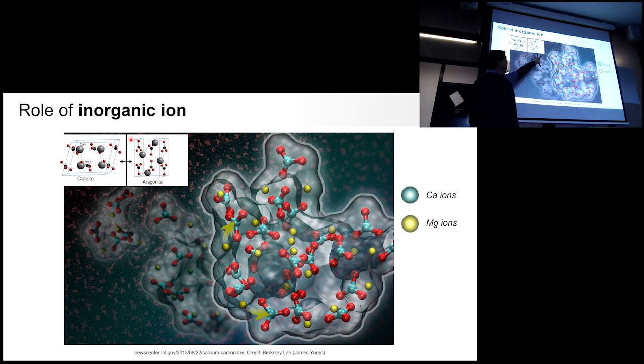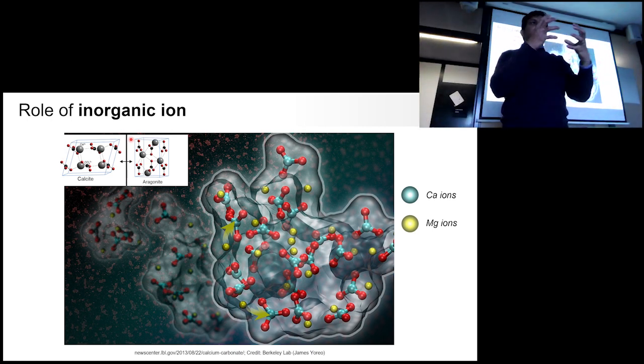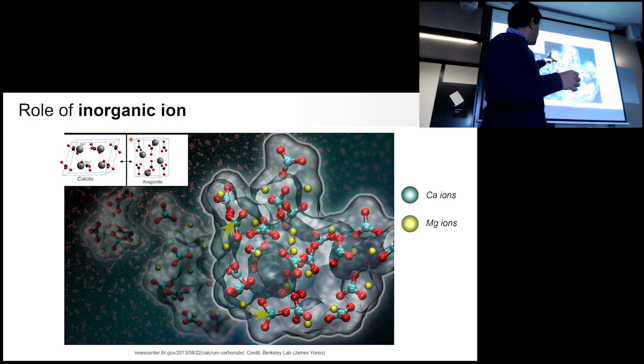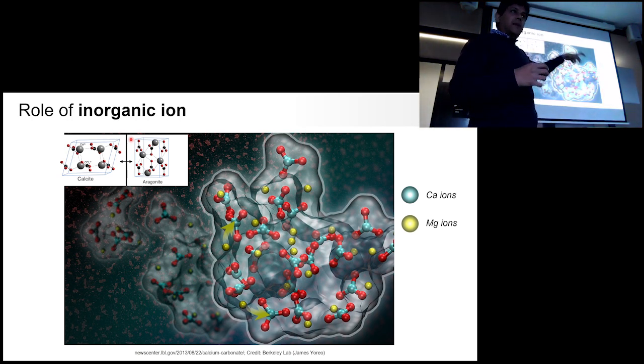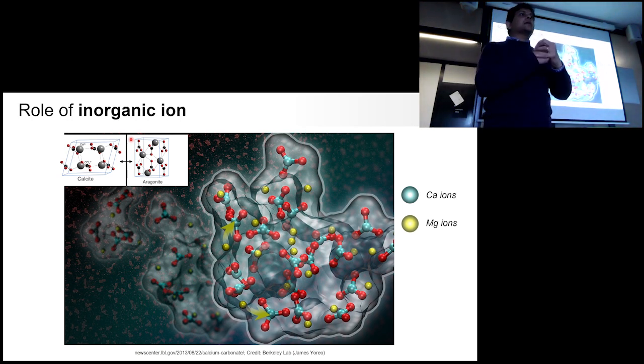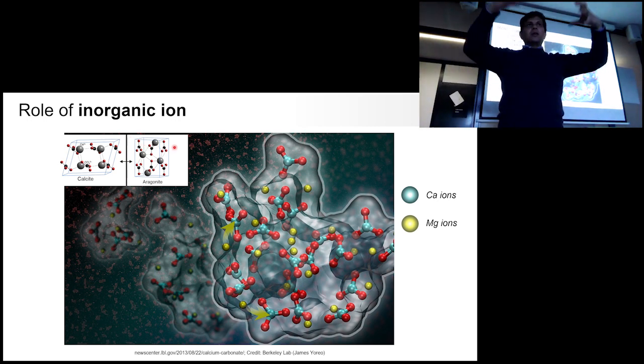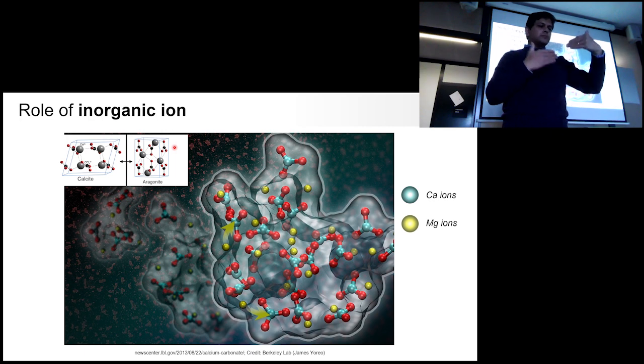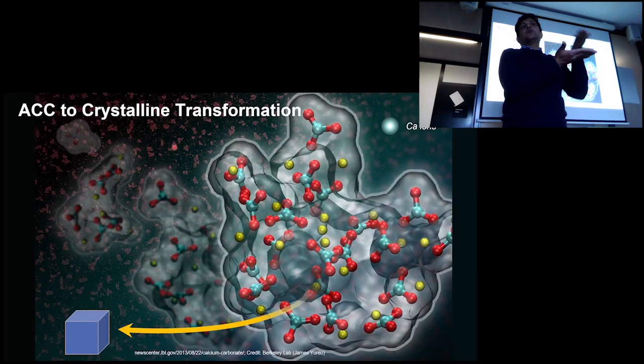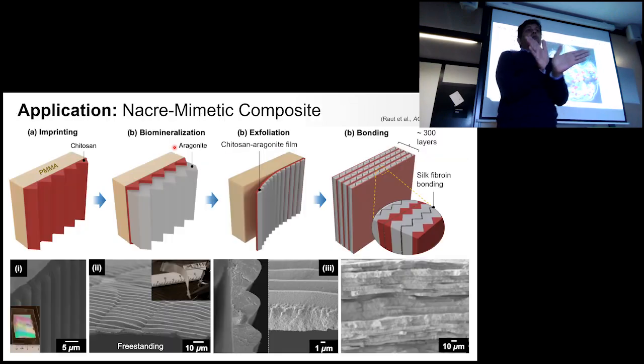And recently, researchers have also shown that while this process is at play, magnesium blocks the kink sites. If you remember, I showed you previously when I was talking about how the crystals grow, that the ions experience the least attraction on the surface, with only two sides, in comparison to where you have three sides.